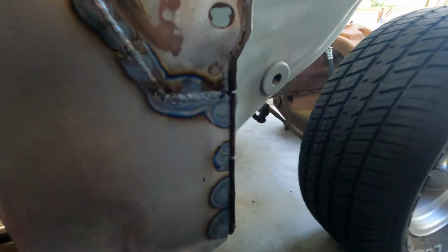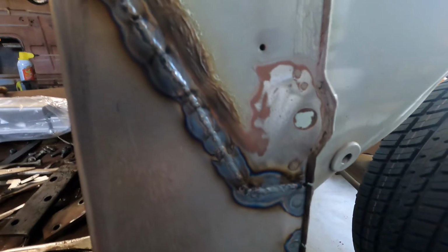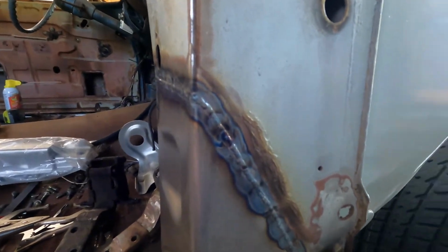Well, here's that finished TIG weld. You can see the smaller size of the weld bead. I'll try and hold it here on the edge. You can just see how flush it is. Look down this one. It's so small. And that weld metal is softer than a wire feed welder is, so it's going to be easy to grind.